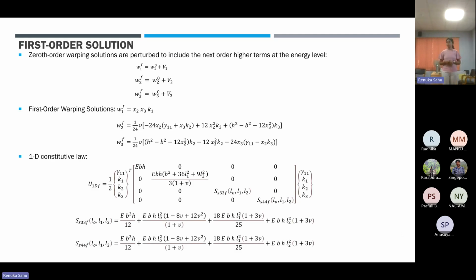Moving on, we did the first order approximation, wherein the zeroth order warping solutions were perturbed to include one order higher terms, and then we get the first order warping solutions doing the same variational formulation. Again we get the 1D constitutive law, and here again the same kind of behavior is there, where material length scale parameters appear in the twist and bending stiffness terms.